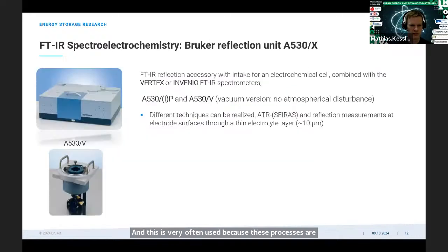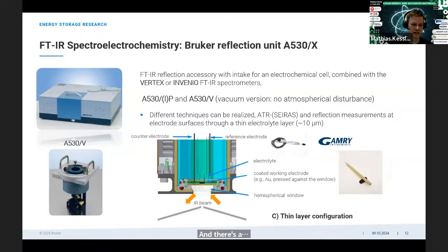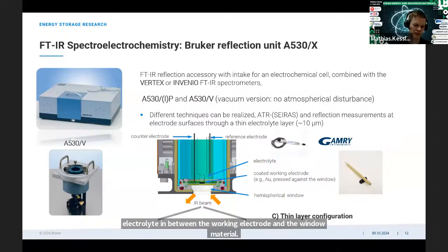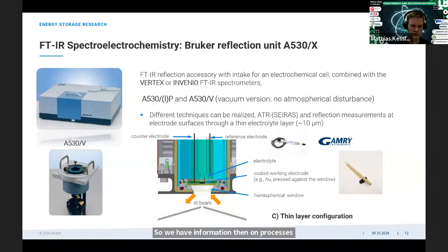And there's a third possibility for how we can use the reflection cell. We can introduce a different hemispherical window, for example, calcium fluoride or barium fluoride, and then this is transparent, so the IR beam goes really into the cell. It's not reflected internally, and then it hits the surface of a working electrode and is reflected on that surface, and then goes back to the detector. And with that, we can measure also the surface of the working electrode, and in addition, the electrolyte in between the working electrode and the window material. So we have information then on processes in the electrolyte and on the working electrode. So this is called then the thin layer configuration.